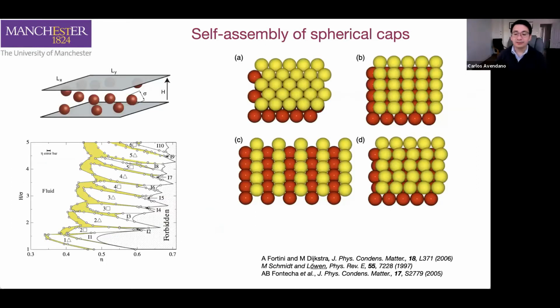Fortunately, we also have a reference system. So several years ago, the group of Fortini and Dijkstra reported the phase behavior of spherical particles confined between two hard walls. And the type of structures that you observe are things that you will, just by playing with the spheres, know that you will form under very strong confinement when the particles can be only constrained to moving in 2D because they cannot move in the Z direction, but they can move in the plane. You know that at high densities, they don't have any other option but to pack in a hexagonal lattice. That's the best packing that you can get.